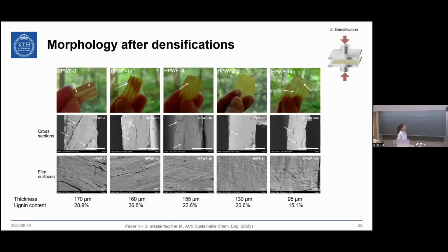So what happens if we densify these materials? We can see from the macro scale that there is a progressive improvement in the appearance of the film. And this is also confirmed by the cross-section, where we can see a progressive diminishing of the amount of gaps and fractures inside the wood film.